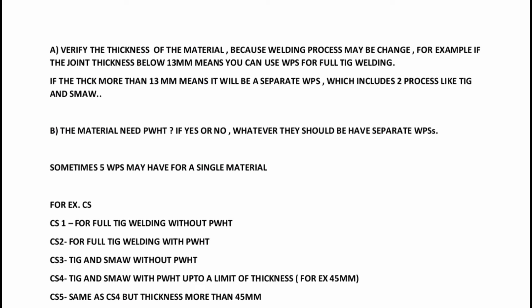First, we will verify the thickness of the material — we will check the joint thickness. If we are using TIG welding only, and then if we use SMAW combined with TIG welding, that gives us one of two process options. TIG-only is for thickness below 13 mm, and TIG plus SMAW covers greater thickness. That looks good for the main WPS.